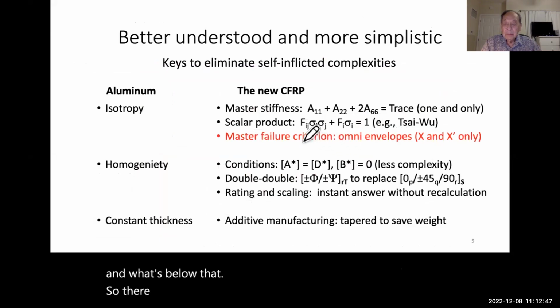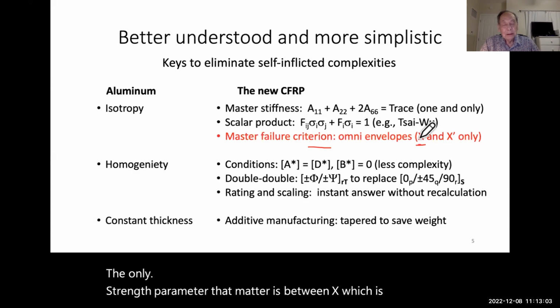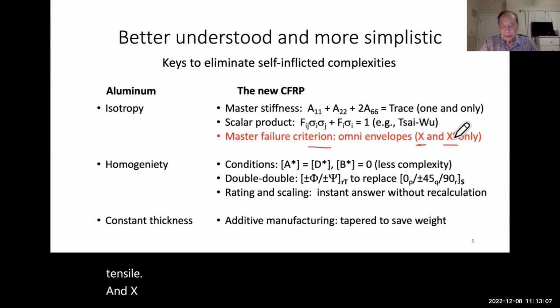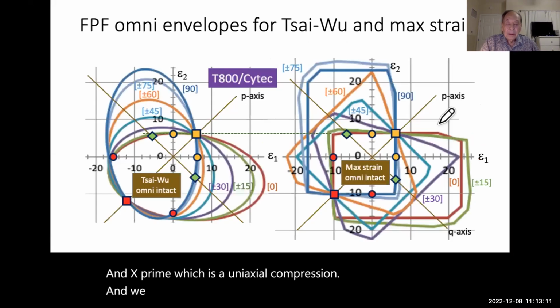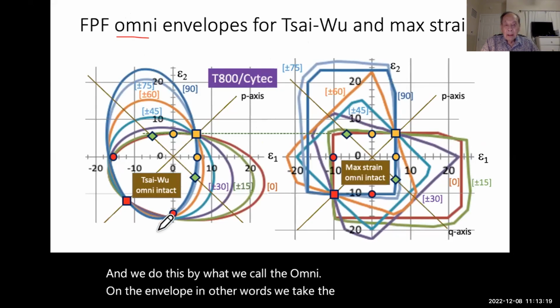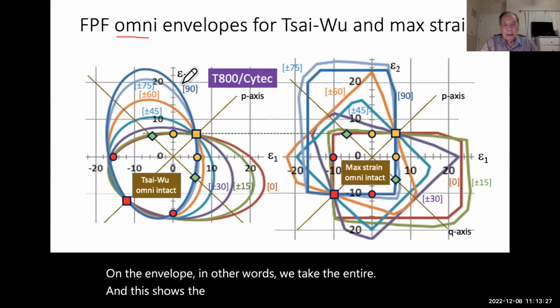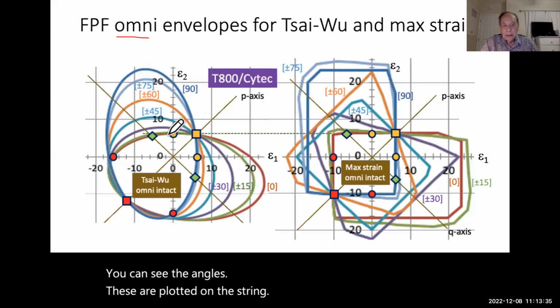So then we talk about failure criterion. Failure criterion, we will show that the only strength parameters that matter are X, which is uniaxial tension, and X prime, which is uniaxial compression. And we do this by what we call the omni envelope. In other words, we take the entire lamination, and this shows the strain in the epsilon 1 and epsilon 2 planes. You can see the angles. These are plotted on the strain basis. And what is left in the middle here, that's a common ground shared by all laminates. This we call the omni